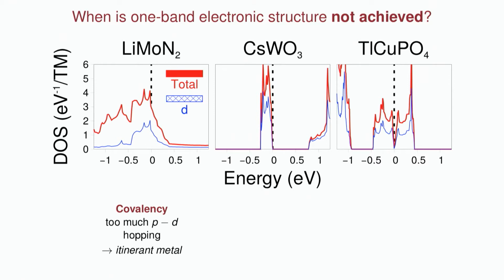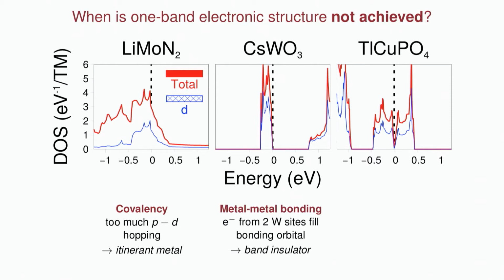Okay, so another thing that can happen, such as in this cesium tungsten oxide case, so here you can see it looks like, okay, we got this narrow level, but you can see it's not half filled in this case. It's completely filled up. And what happens here is you can have too much bonding or interaction between the metals themselves. So in this case, the crystal structure is complicated enough that you have these multiple tungsten sites. Tungsten is a 5d element, and those d orbitals are less localized, so they start overlapping and interacting with each other such that you form a bonding and an anti-bonding level, your usual thing from chemistry.